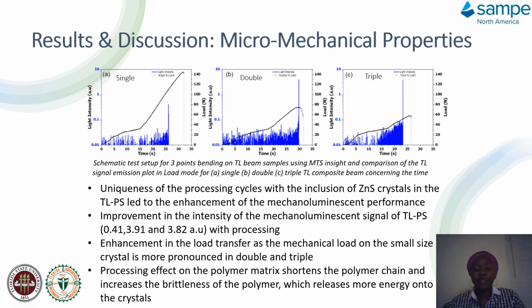And this improvement is due to the inclusion of TL as well as an enhancement of the load transfer of the zinc sulfide crystal particles, which can move from one crystal to another, because they are much smaller and evenly dispersed compared to the single processing, which has higher crystal sizes. And this processing effect on the polymer matrix also shortens the polymer chains.